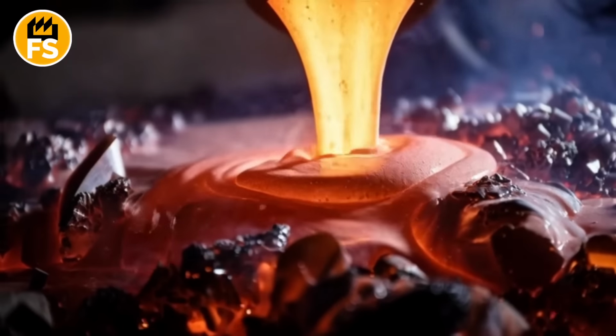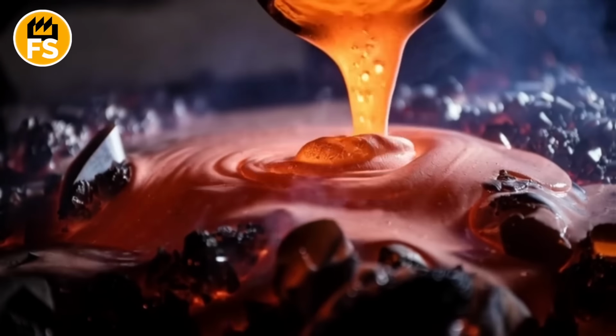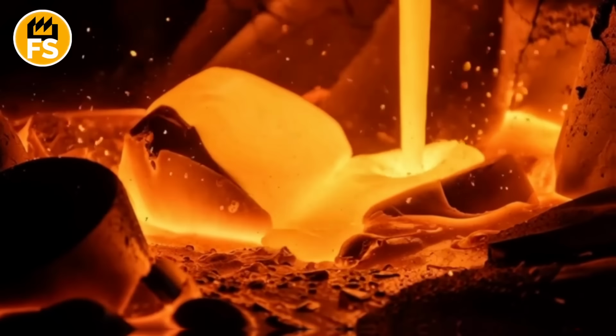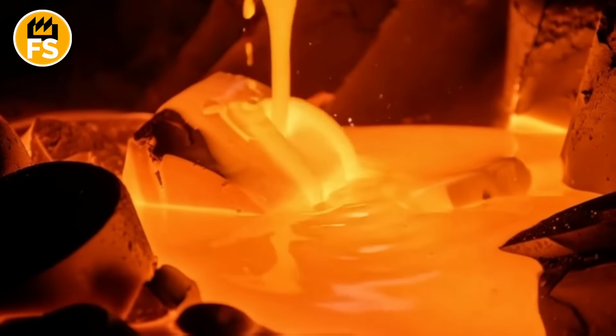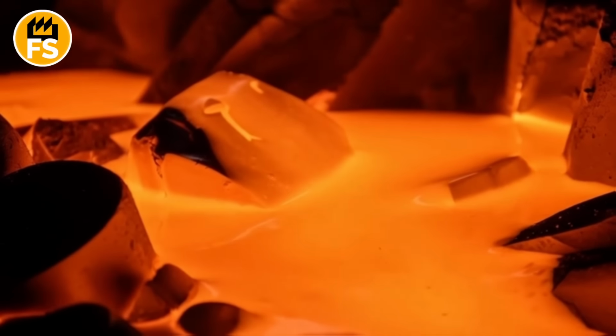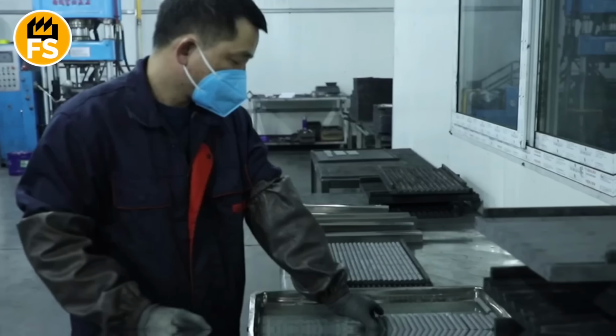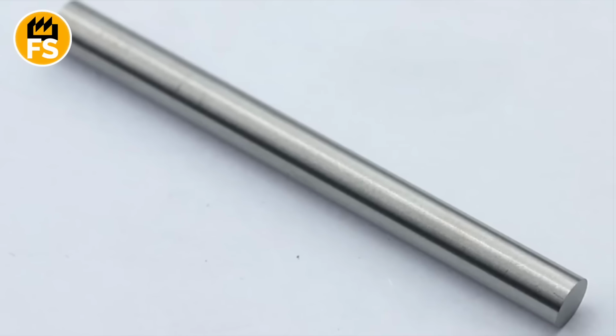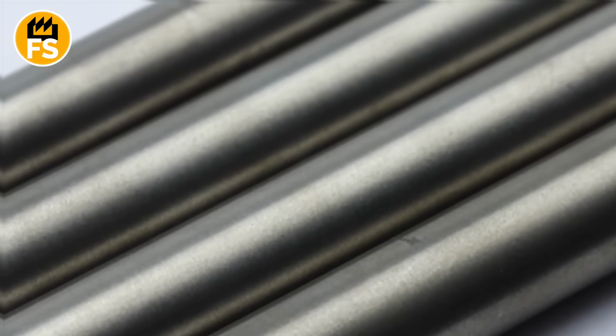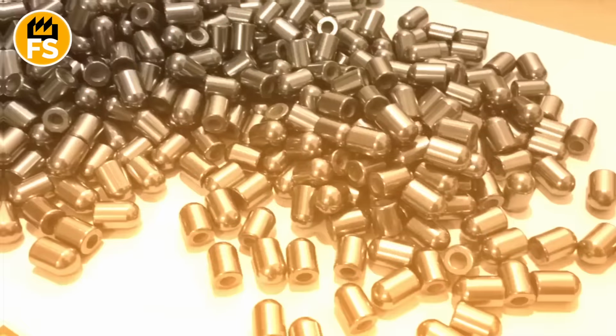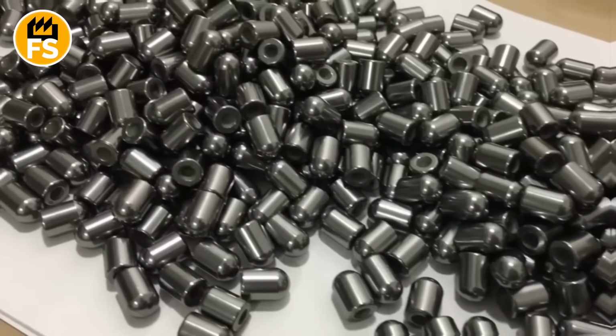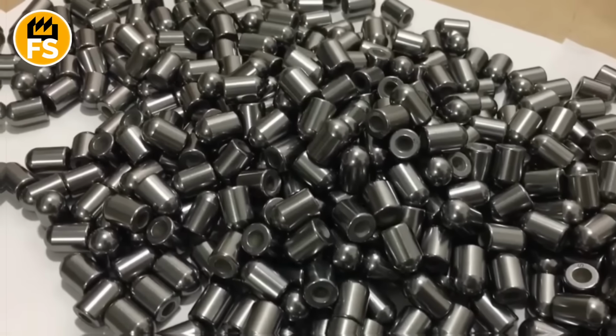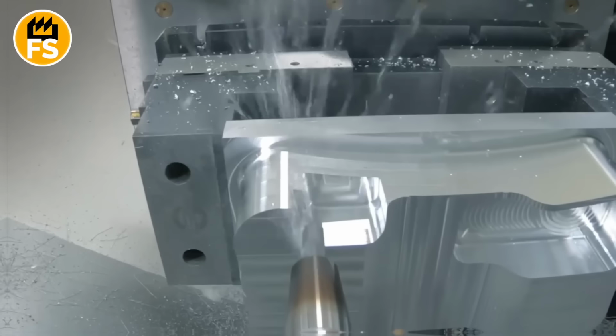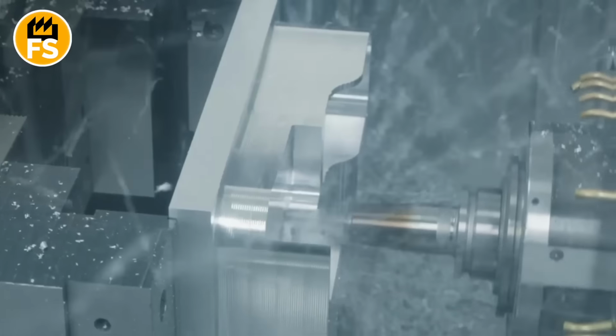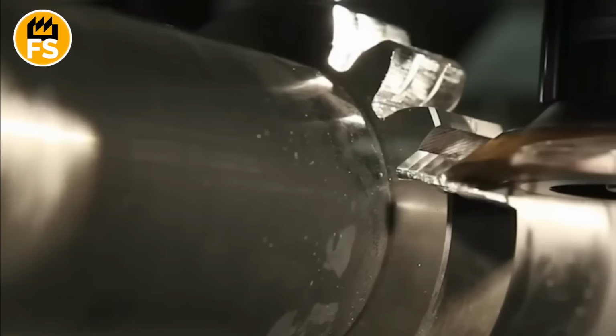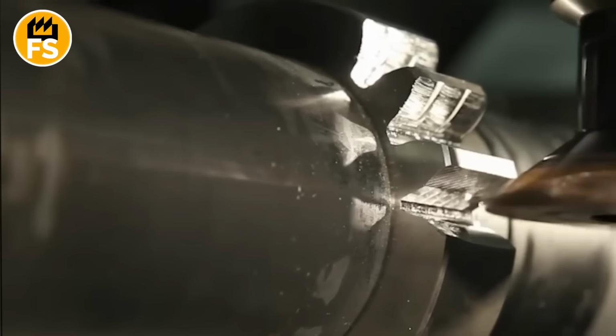Molten cobalt, like a river, floods every gap between tungsten grains. It acts as a binding agent, tightly enveloping each super-hard grain. The structure takes on the appearance of a perfect brick wall, where tungsten grains are the bricks and cobalt is the mortar. After cooling, we get a cemented carbide that demonstrates phenomenal synergy. It has hardness comparable to diamond, but thanks to the cobalt matrix, it has enough strength and toughness to withstand the impacts and vibrations that are inevitable during cutting.